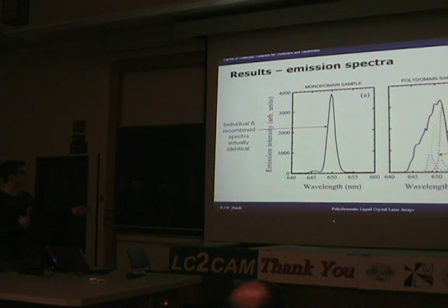One which we deliberately made with quite poor alignment qualities. So this introduces domains within the liquid crystal with slightly different chiral pitch. And the chiral pitch, of course, will affect the lasing wavelength that's emitted in that region. So if we look at the spectra of each individual laser spot, which is the broken lines here, you can see lasing, nice tight line widths from each individual spot, but subsequent spots don't match up.